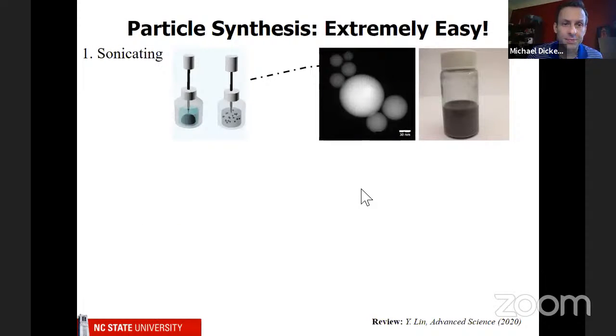So for example, one way to do it is by what's called sonication. Basically, this is just vibrations, like shaking. And we can take the liquid metal and form particles. And this is what the solution looks like. It kind of looks like milk a little bit, but it's gray. And if you look at it with a fancy microscope, you can see the particles are very small, about 100